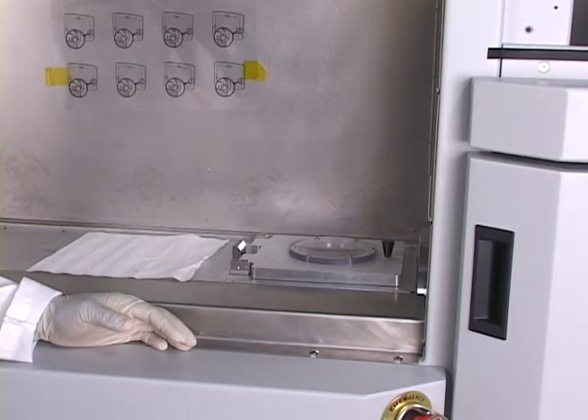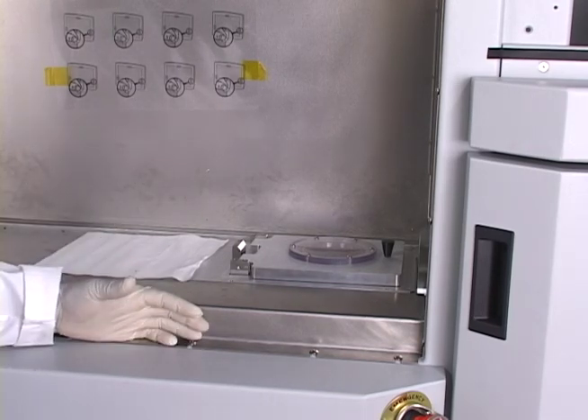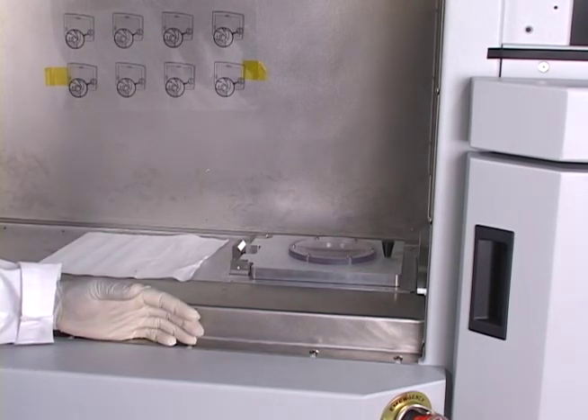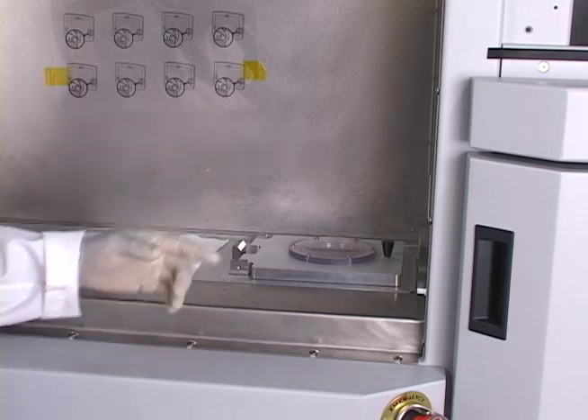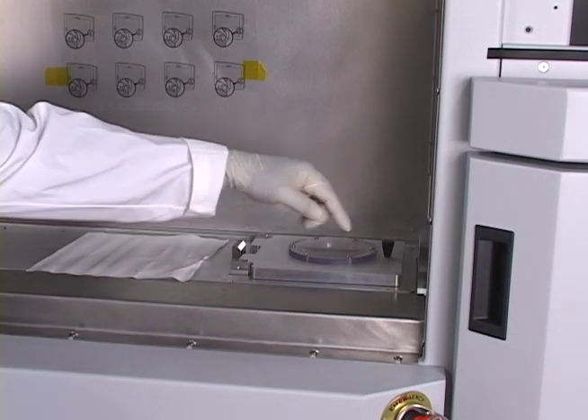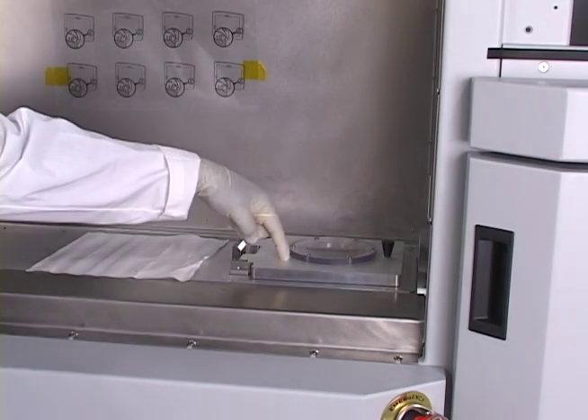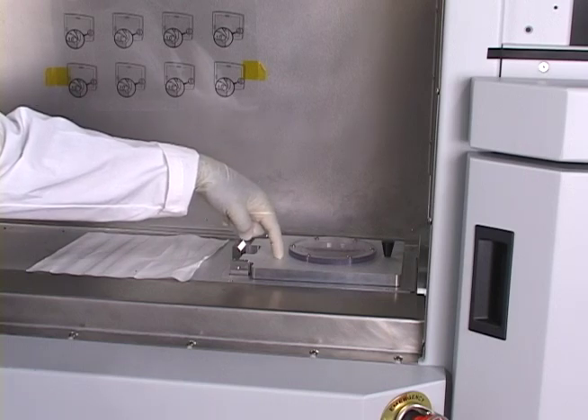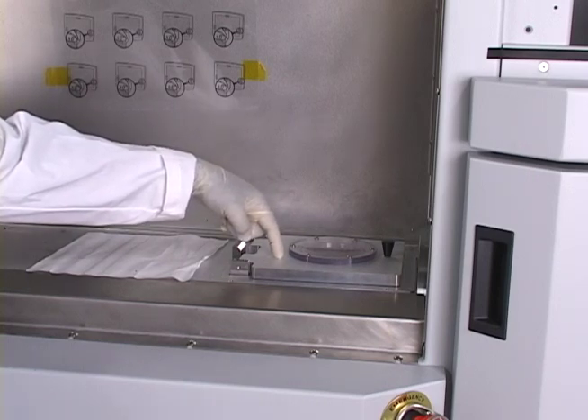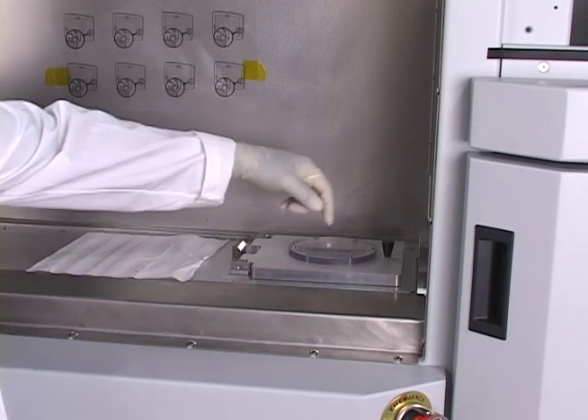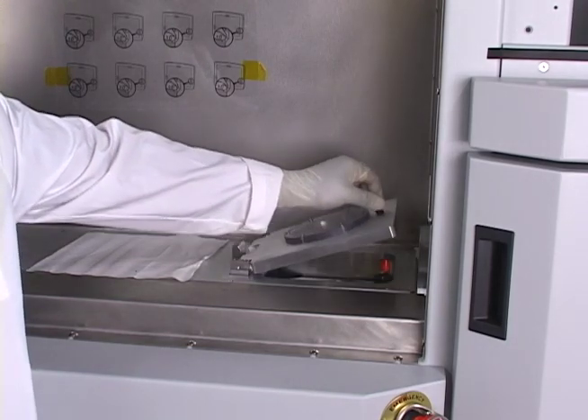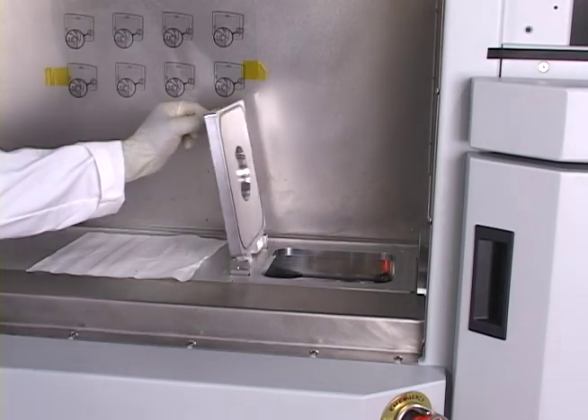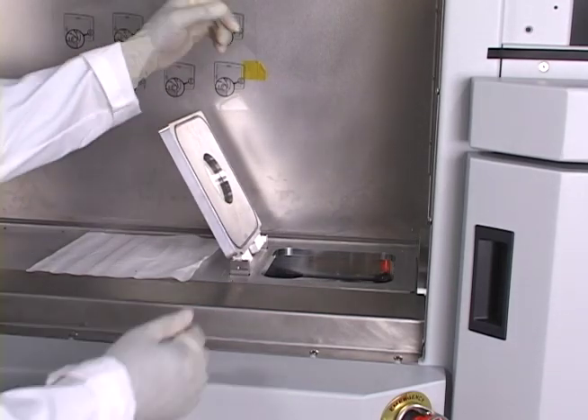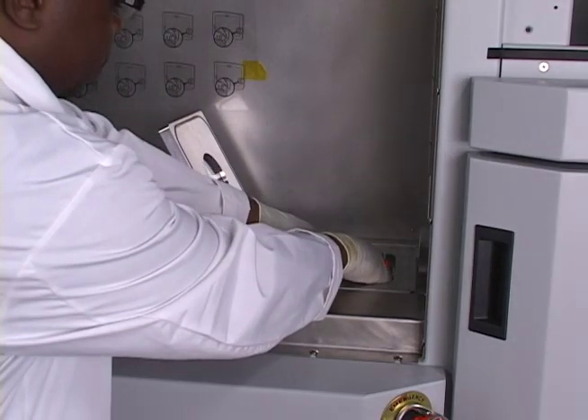So once the script has been executed, or once the recipe has been executed, the sample has now been moved from the deposition chamber back into the load lock. And then once this has been devacuumed or actually brought up to atmospheric conditions, we can now open up the load lock chamber, and take out our sample.